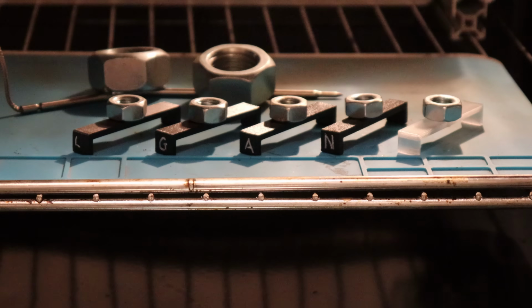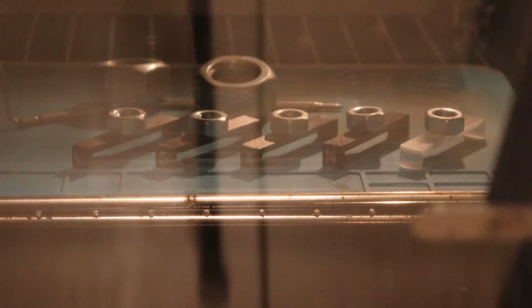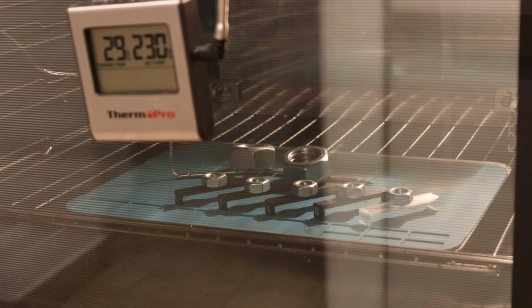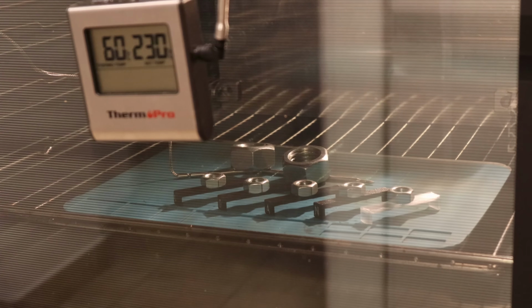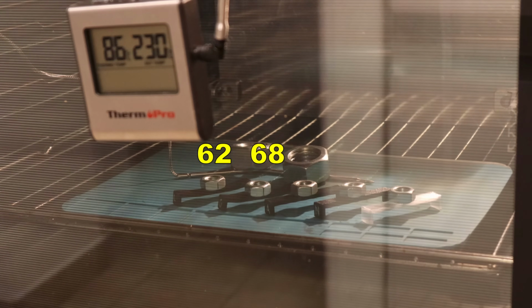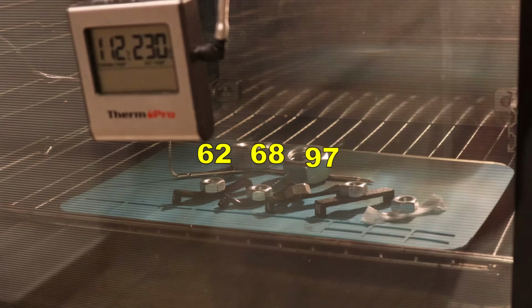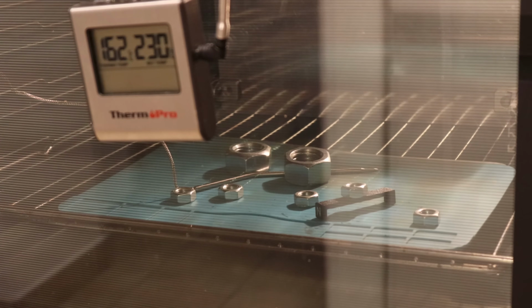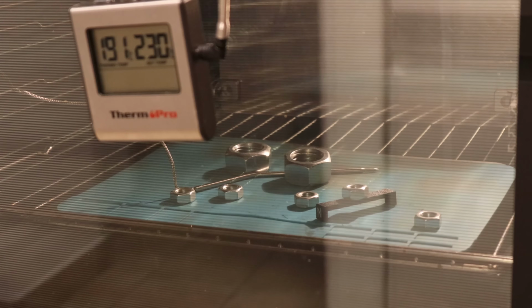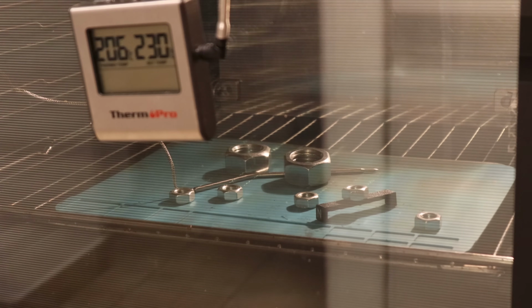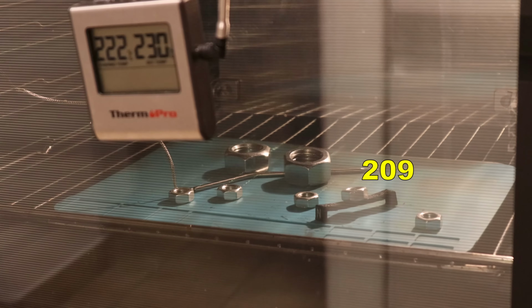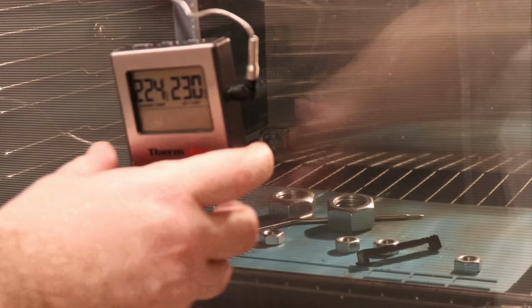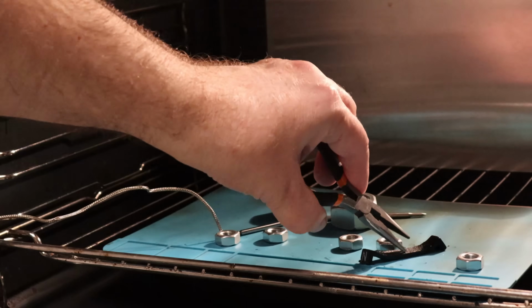Temperature test in the oven, from left to right, PLA, PETG, ABS and nylon. And I want to record the temperature of the first noticeable deformation. And of course the first one was the PLA, shortly after that the PETG, and then the ABS. And I decided to take out these filaments because I'm expecting much higher deformation temperature of the nylon. Let's jump in the time. And a little bit above 200 degrees Celsius I noticed that it starts with deformation. And I stop to check how flexible it is. This is the most obvious difference between these 4 base materials.